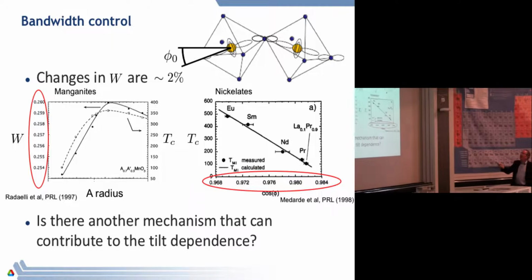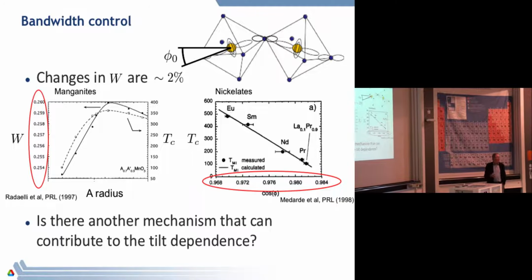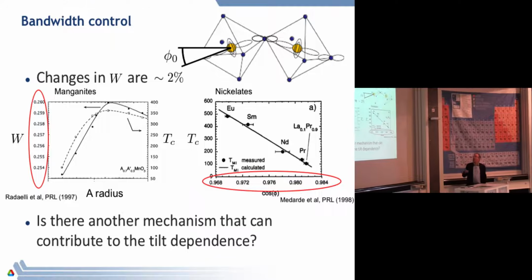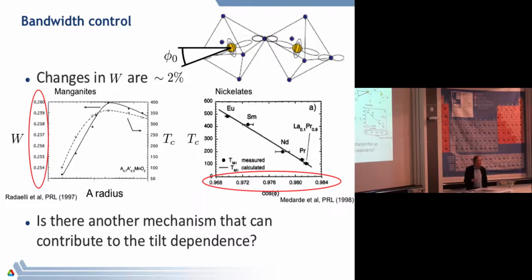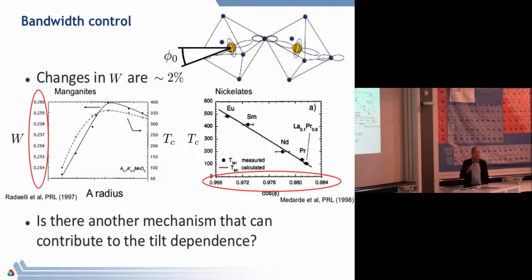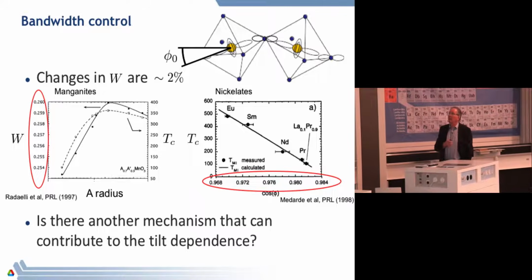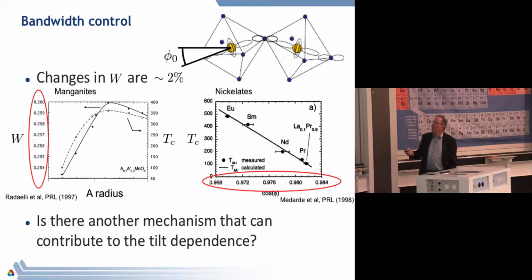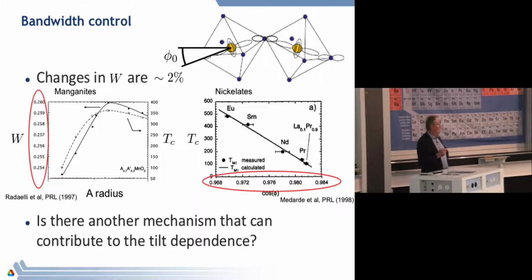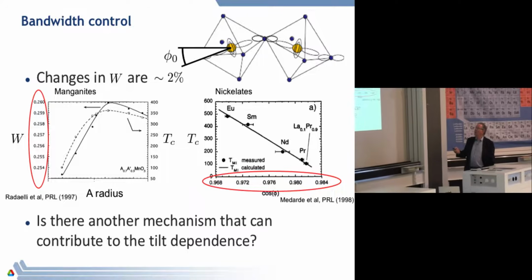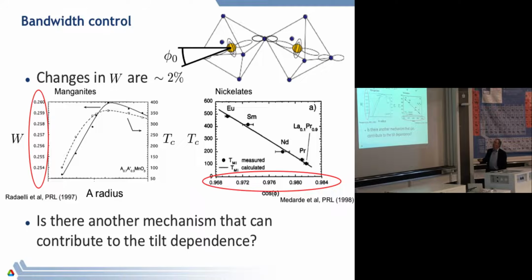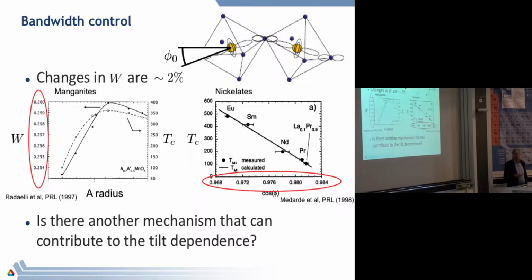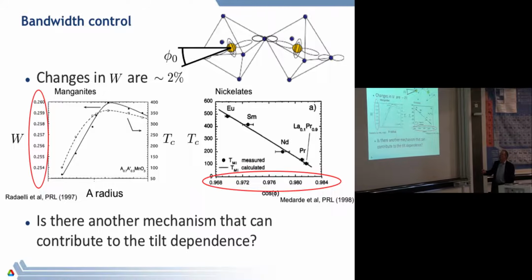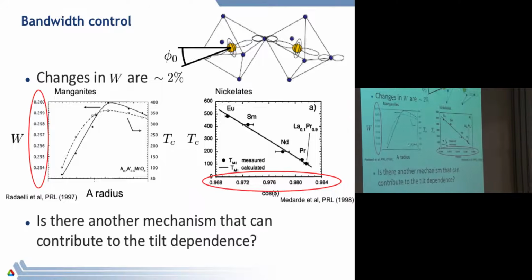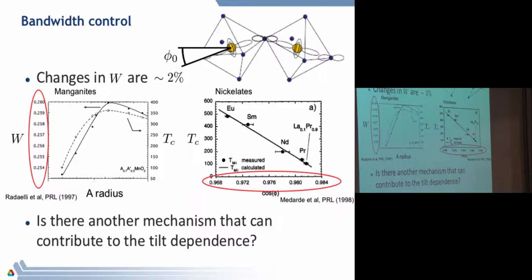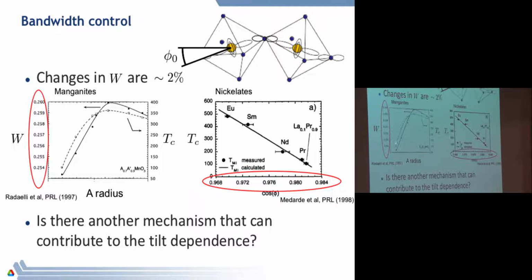And so, simple thinking says, well, okay, this ion isn't changing, so the interaction strength isn't changing, the doping isn't changing, but the bond is changing, and therefore I must be changing the bandwidth as a function of angle. And indeed you are. However, it doesn't look like you're changing it very much. So here's one class of materials, manganites, that I will talk quite a lot about in a moment, where the transition temperature for one of these Mott transitions varies from above room temperature to 0 by changing the cation radius by a little bit. But if you calculate the change in the bandwidth, it's only 2%. And it's kind of remarkable that that 2% change can produce this big one.